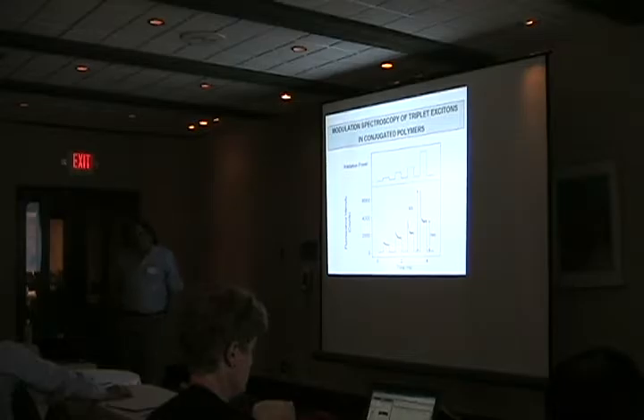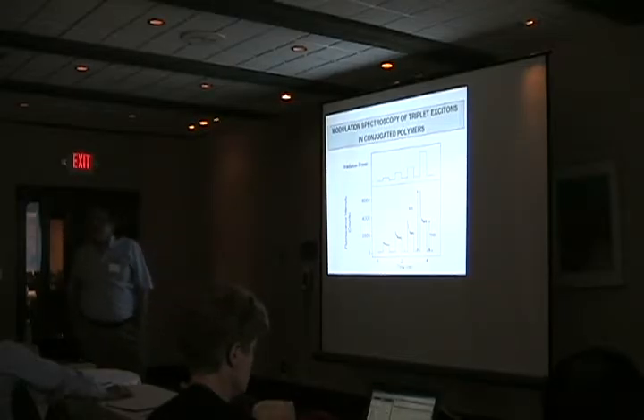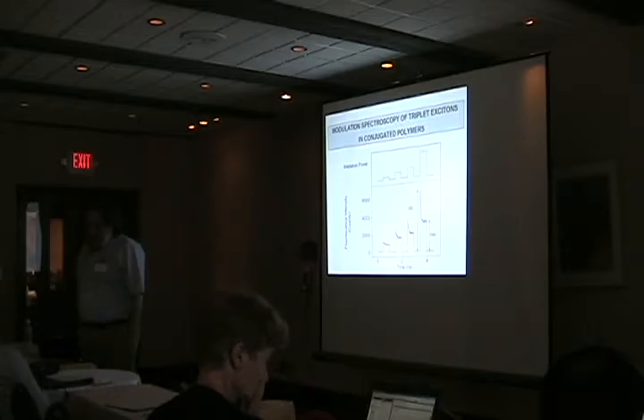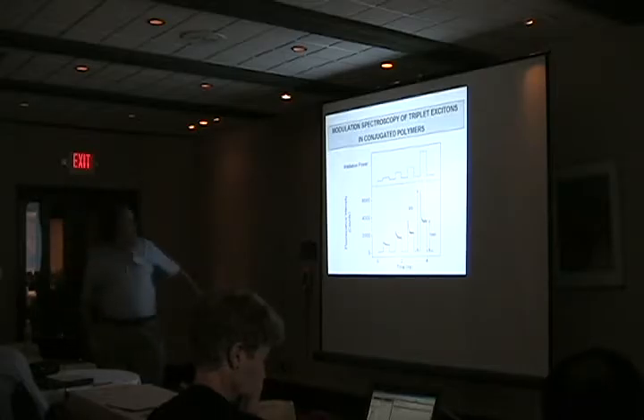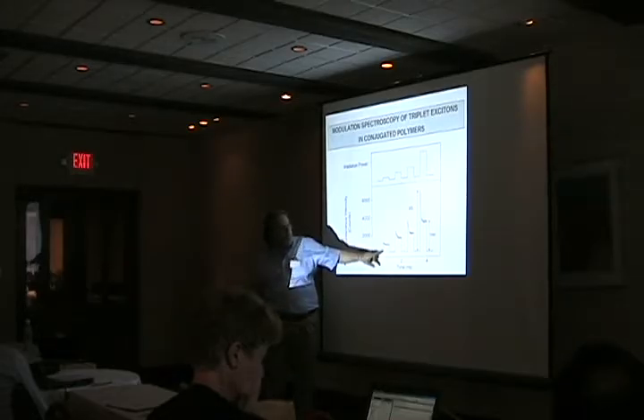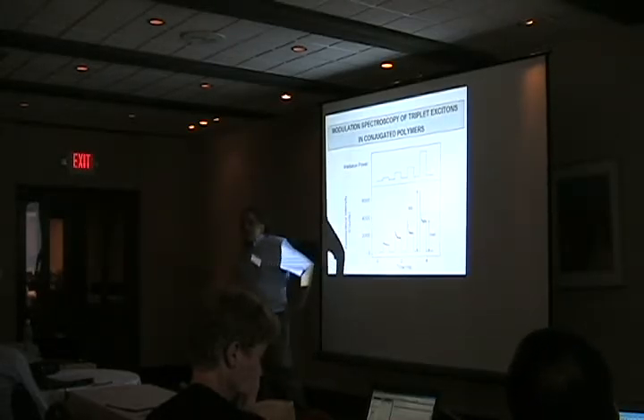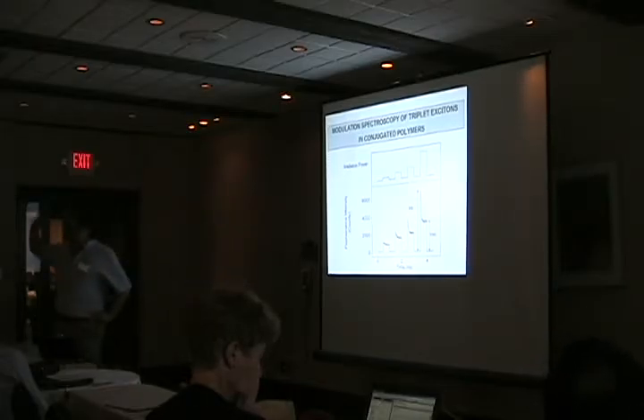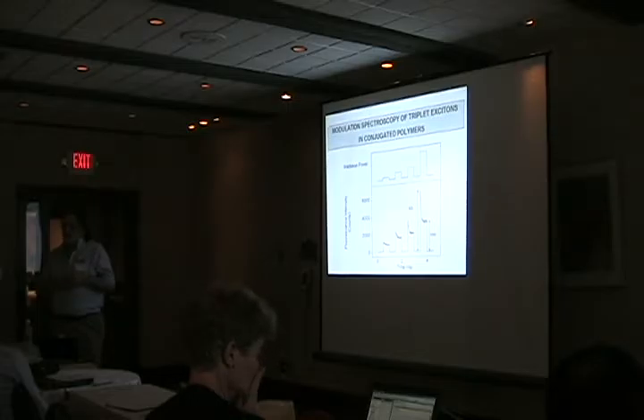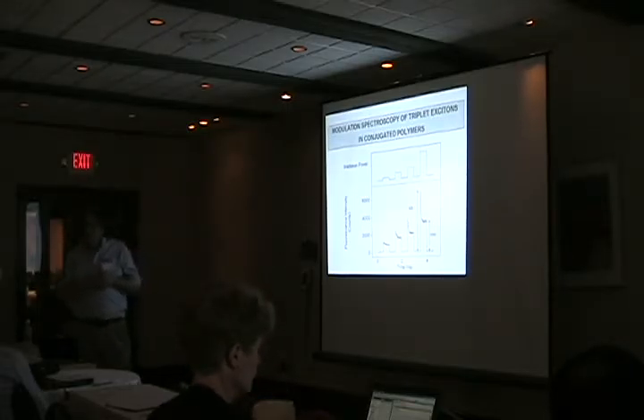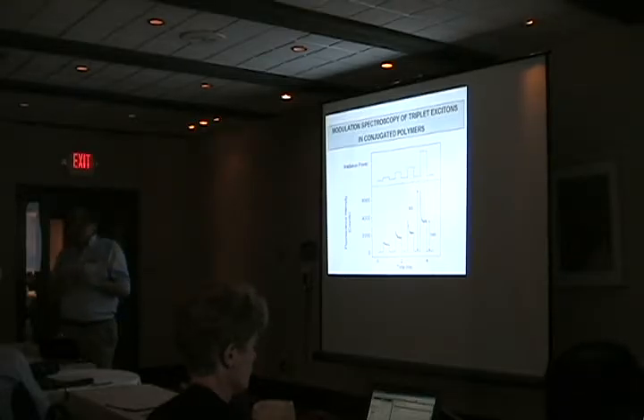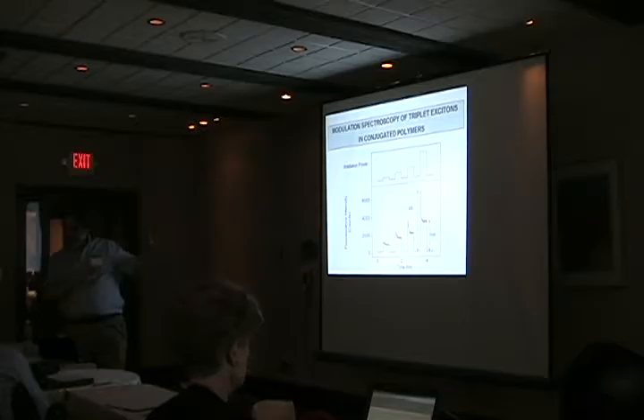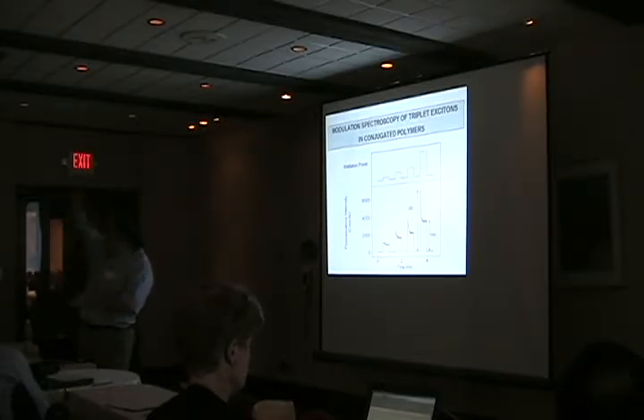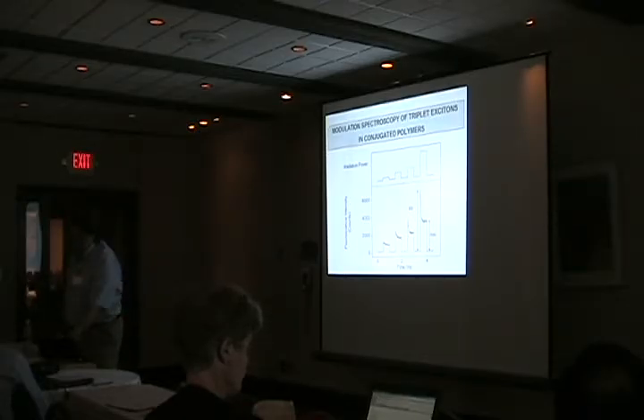Now, it turns out I've been talking about light excitons, singlet excitons, fluorescence, they're not really very excitonic. But you can also look at the triplets or dark excitons. And the way you do that is you take a single nanoparticle, turn the laser on, and this is some 10,000 cycles, but it's one particle. You turn the laser on, and you see on the microsecond time scale, depending on the light power, the emission go down. And what you're doing is you're changing the time average probability of a dark exciton to be in the chain. And the dark exciton, which is a triplet state, is a very efficient quencher of singlet states. So you're turning the system on, it emits, and then it builds up a triplet, and that makes its emission go down. So you can do triplets, and we did a lot of work on triplets and localization and exciton interactions.